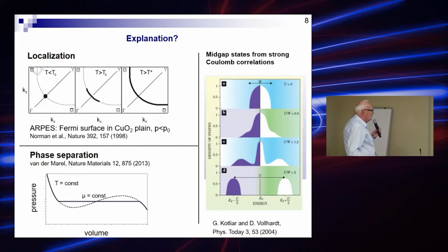The third is strong electron correlations. This is results of Kotliar. You see that for very large Coulomb interaction we have insulator, valence band and empty conducting band. Then in between we have mid-gap states, and finally for very low electron interactions, correlations, we have metallic state.